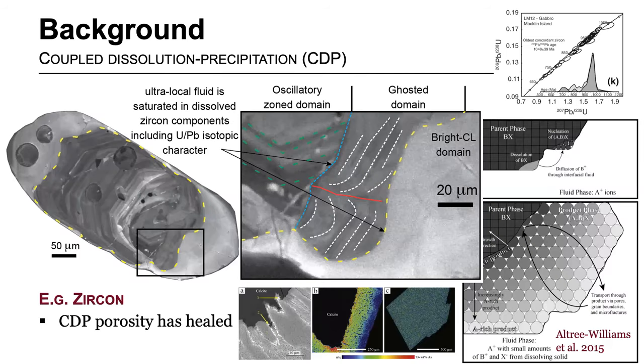So our research question is whether this process of coupled dissolution precipitation is common in minerals like monazite and zircon that we use for geochronology. We often see complex textures in cathodoluminescence, like is shown on this zircon, with a ghosted rim. Our new interpretation of these rims is that at the interface of the fluid zircon reaction, the dissolution of those zircon components includes uranium and lead isotopic character, such that when the new zircon precipitates in coupled dissolution precipitation, it can inherit or partly copy that uranium-lead isotopic character.